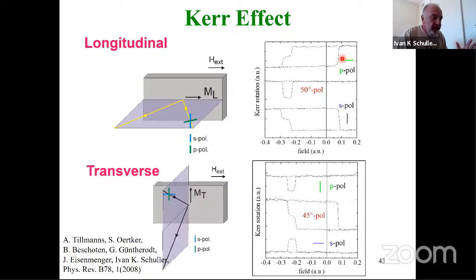And in fact, if you look at the transverse MOKE, you discover the very same thing. At some intermediate angle, there is a step. If you look at the Kerr rotation, on one side of the loop, there is a Kerr rotation in the perpendicular direction. So what this means is that the magnetic moment of this exchange bias material, on the left-hand side, rotates. On the right-hand side, it just reverts by domain wall motion, okay?